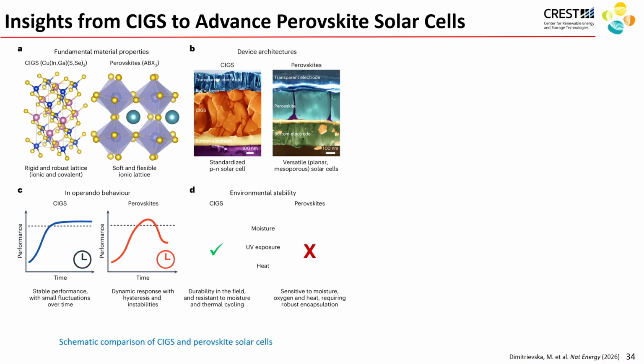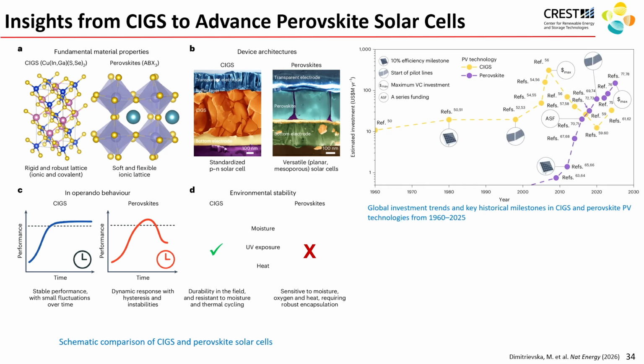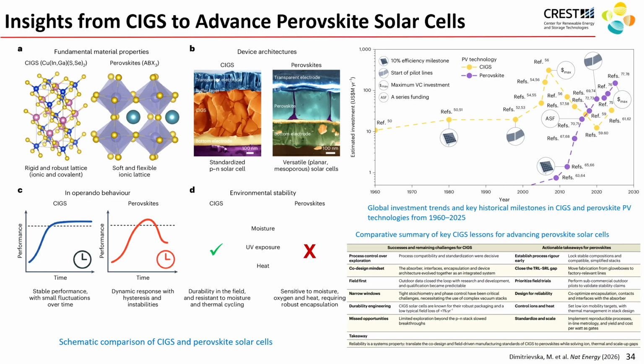I also would like to point your attention to this paper that I recently read comparing the evolution of perovskites to the evolution of CIGS technology, copper indium gallium, I think sulfide or selenide, and basically these are solar cells that have gone through their own evolution. They became relatively efficient. Their adoption slowed down quite a bit because of the complexity of the composition. There were a lot of elements involved in device stability, and that meant that in order to achieve device stability, you had to deal with the system overall, not just optimize one parameter and leave the rest, and optimize things separately. So there are a lot of important lessons for us to learn from the CIGS system that could be applied to perovskites.